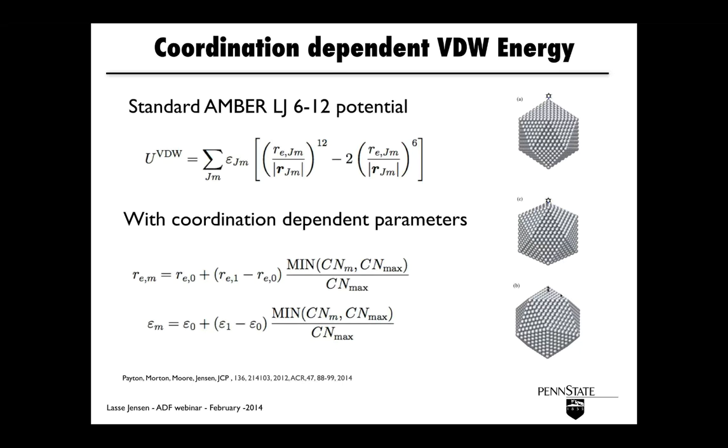So, for example, describing the nitrogen here or the purine molecule, its interaction with the silver atoms depends on the local coordination environment of that silver atom. That's described here by this formula, which is just a linear interpolation, counting nearest neighbors and a little bit of the second shell as well, to give you a value between 1 and 12 for these sites, which means a coordination-dependent force field allows you to differentiate binding between low coordination sites and high coordination sites.